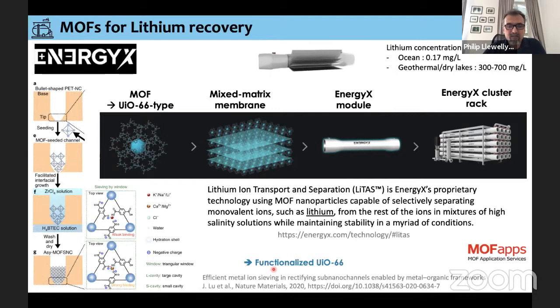If you look at one of their recent publications, what they've tried to do is actually engineer the membrane itself. Here we have a PET membrane. They've put in bullet-shaped holes, and the idea is to grow the UiO-66 material inside these pores. What they say is that they have sieving by window. This is the triangle window of the UiO-66. We have here a dicarboxylate linker. They say that there's stronger binding with 2+ ions, for example calcium and magnesium, and less so with these ions here. This is one way to recover lithium.